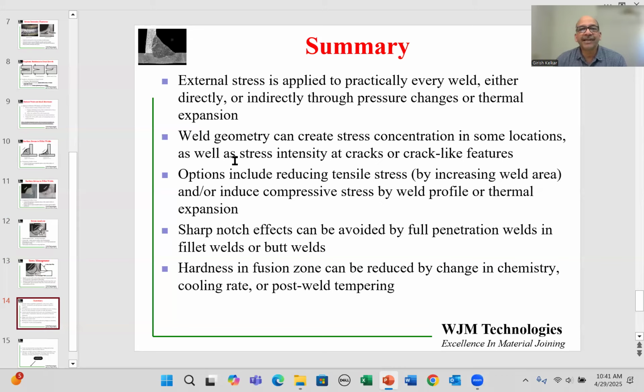The weld geometry can create stress concentration in some locations as well as stress intensity. So the weld is not a homogeneous and a simple shape. So it has stress concentration effects at the toes of the weld. It has stress intensity effect at the root of the weld. In addition to that, there could be porosities and cracks in the weld, which will aggravate the situation.